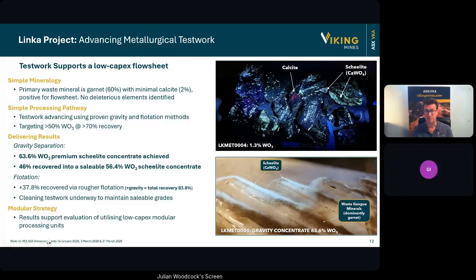The gravity separation proved extremely effective. The lower image here shows the sample going through gravity separation test work on a Wilfley table. This white material here is the scheelite, which is concentrated, and the waste material, the gangue, is the browner color, which is the garnet. And we attained in this sample a premium scheelite concentrate grade of 63.6%. In that process, we recovered a total of about 46% of the contained scheelite into a concentrate grade of 56.4%, so still above that target of 50%.